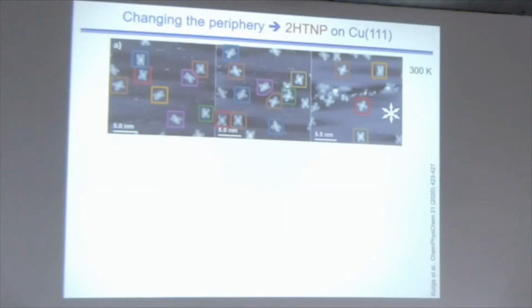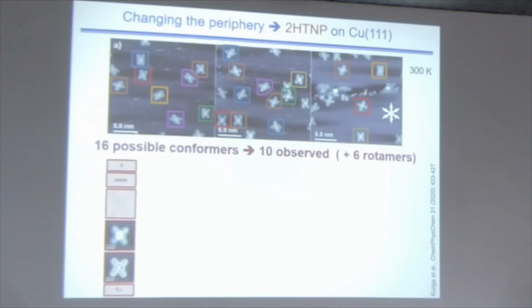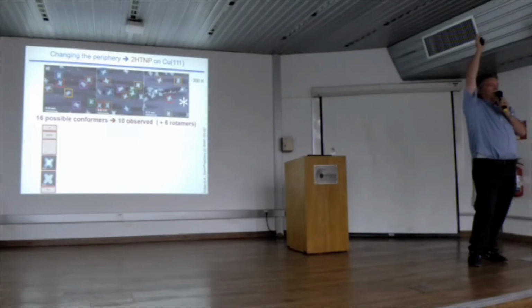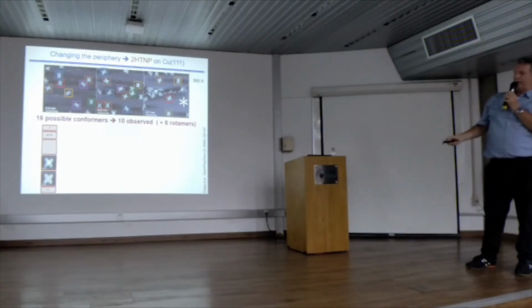And out of the 16 possible conformations, you will only observe 10, because for 6 you have a rotamer. That means if you rotate by 180 degrees, it looks alike. And of course, you cannot differentiate. And that's what we did then. So we identified all of them. And if the groups are looking outwards, we call it alpha. And if it's inward, we call it tau. And so this is our alpha friend.